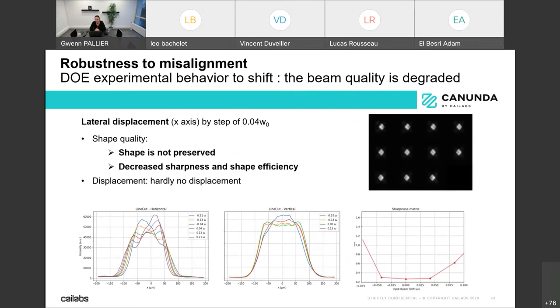Now we will discuss DOEs, and we will be pretty short on that, but I think it's very obvious when you look at that. Here, at the maximum, we are only moving off 20% of the waist, and you see that this is no more top-hat at all. The energy is definitely shifted, and it is not homogeneous anymore. So the shape quality is actually not preserved, and the sharpness and the shape efficiency are decreased with a very small shift of the beam. There is no displacement because of the way this is done.